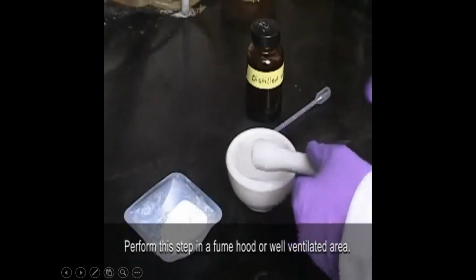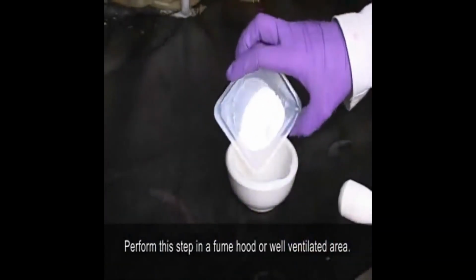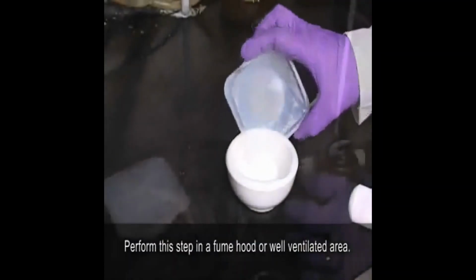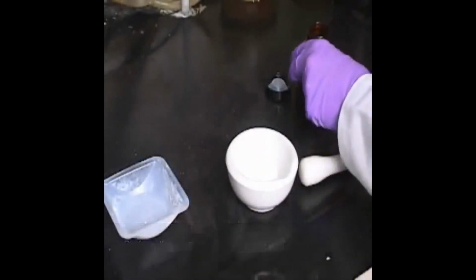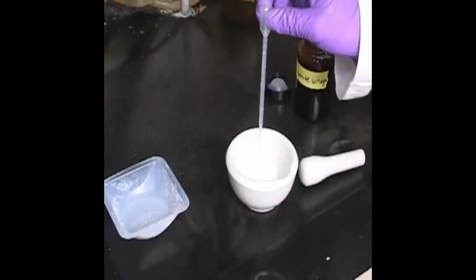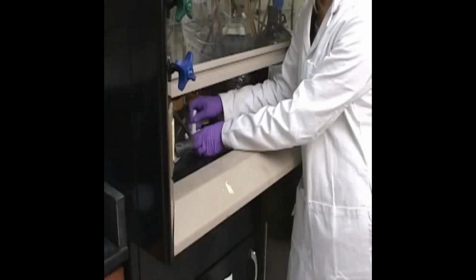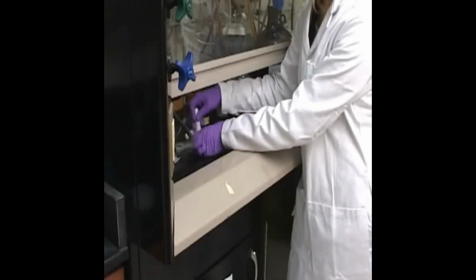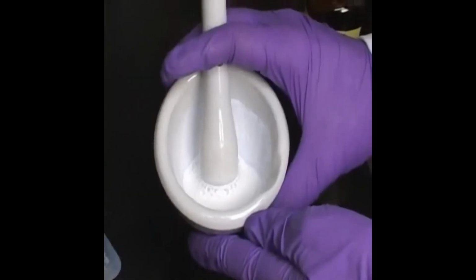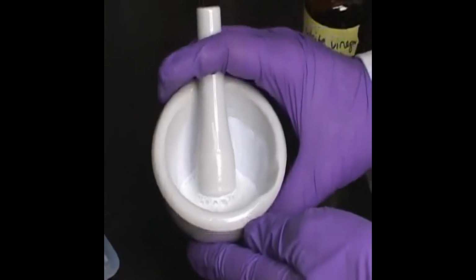Titanium dioxide suspension. Have a look. Step 1. Start with 6 grams of titanium dioxide powder in a mortar and pestle. Under a ventilated fume hood, slowly add vinegar in 1 milliliter increments to the solution, grinding well each time. The process should take around 30 minutes and will result in a very white, milky, paint-like solution.